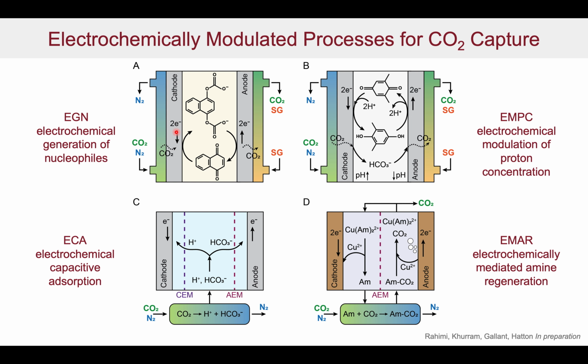And when we get the reduced quinone, it will react very strongly with the CO2 to form the biscarbonate, as shown here. This can then be taken to the anode side, where the quinones are reoxidized, and the CO2 is released, and we regenerate the sorbent. So this is a cycle in which we have a direct interaction.